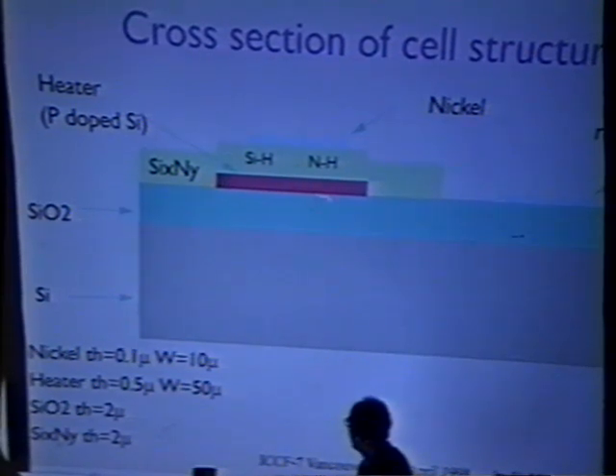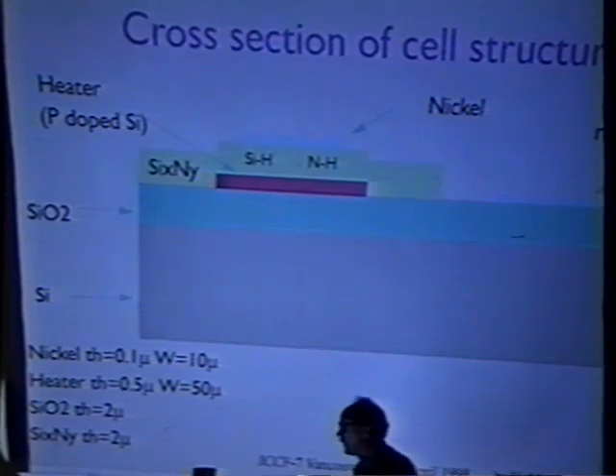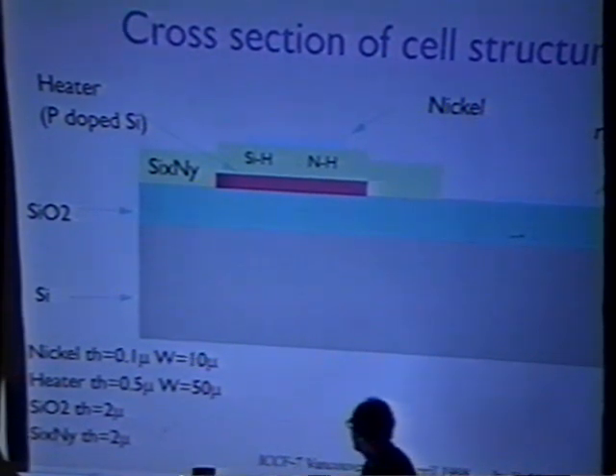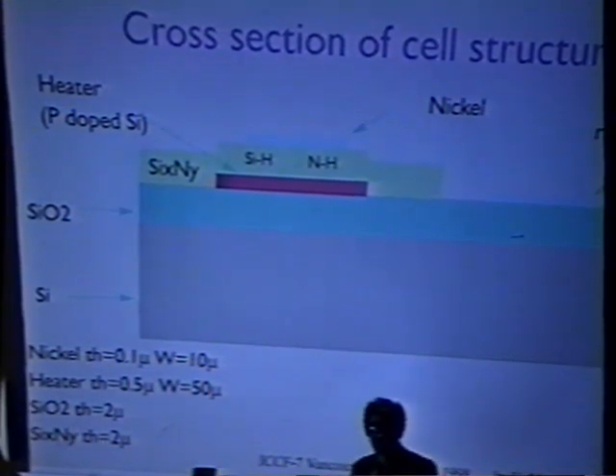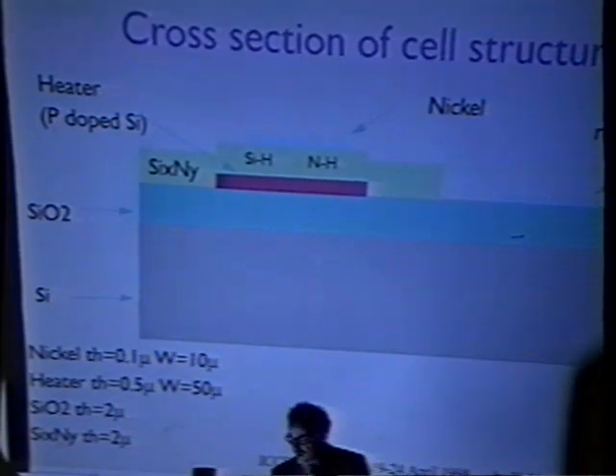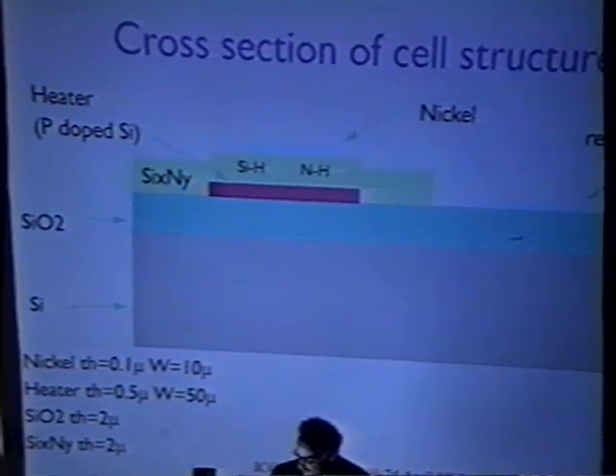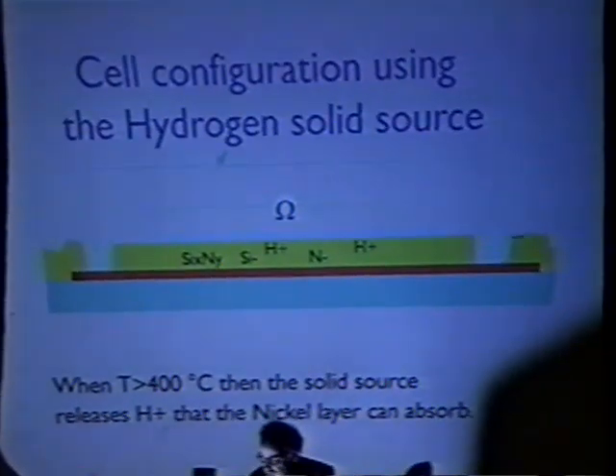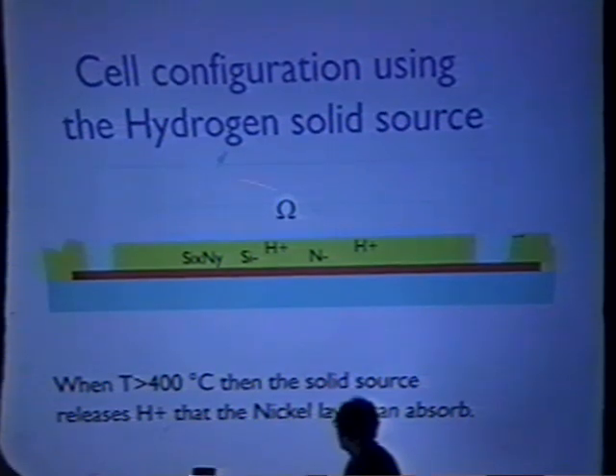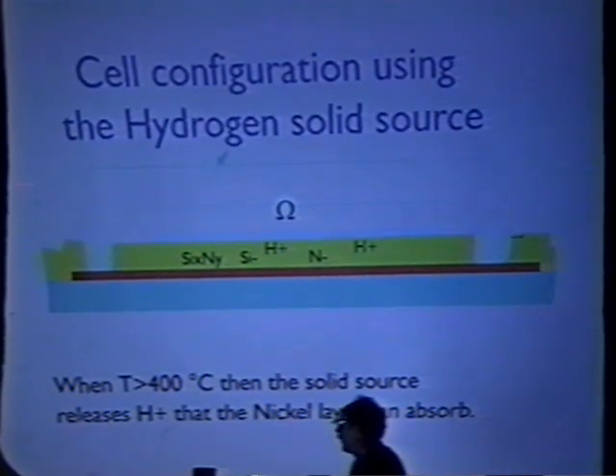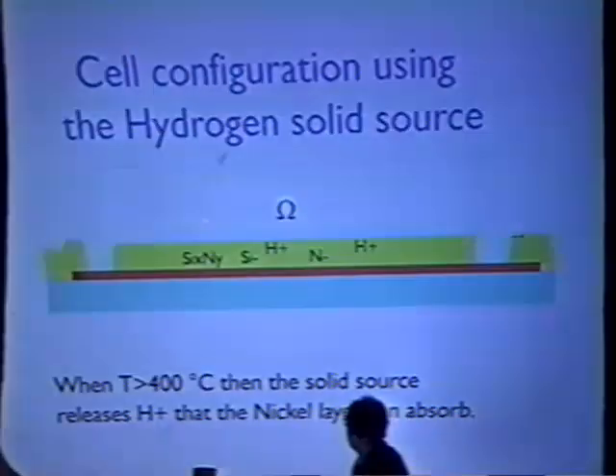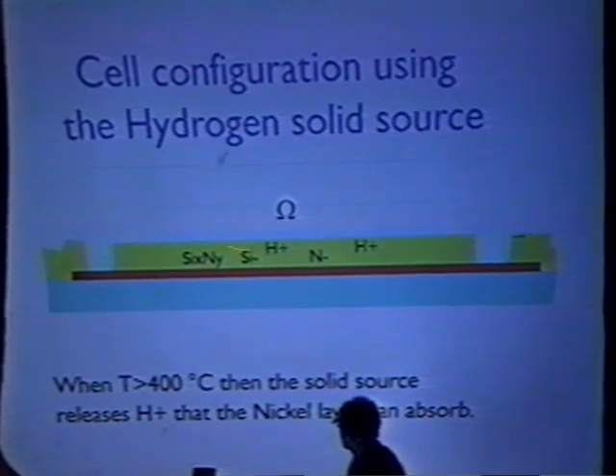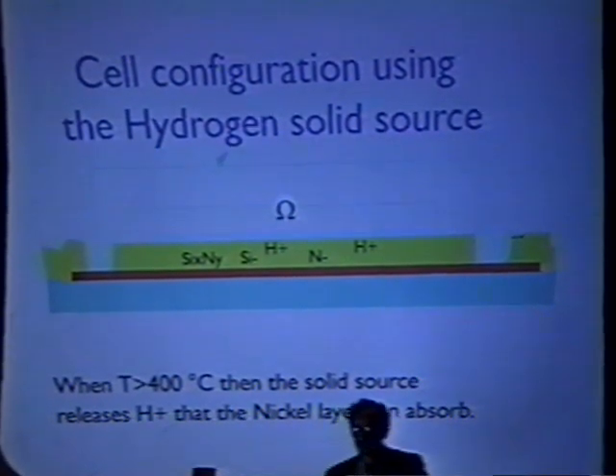And here we have the heater, a polysilicon layer. The thickness of this layer is 0.5 microns. And below we have a silicon dioxide, just to separate electrically the heater from the substrate that is a standard silicon substrate used in microelectronics. Here we have the electrical configuration of the cell, nothing special. The heater was biased by an external power supply, and the nickel electrical resistance was monitored by a standard multimeter.